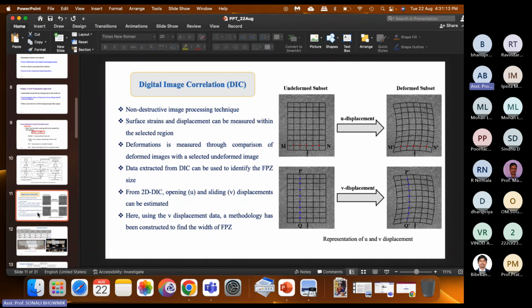This is a very long process of the digital image correlation technique, where we are not only dealing with the algorithm, we have to prepare the sample. And as I mentioned, in that approach we are always considering a pre-existing flaw or crack size, which experimentally we call the notch size. By preparing those notched beam samples and clicking images at particular intervals of load and time, we get those images, and the next step is a rigorous analysis of all those images.